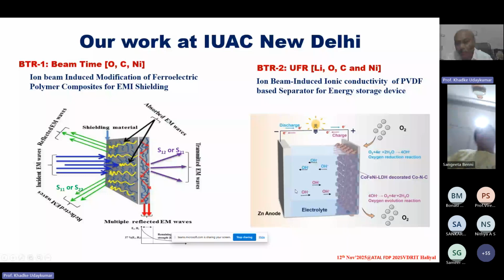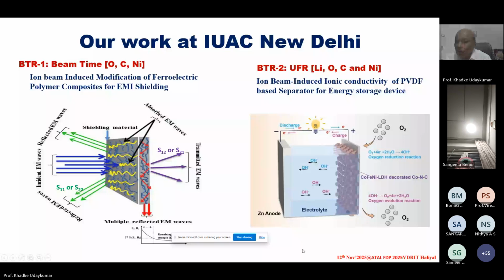So what our team has thought of is to put a layer between these electrodes, but treat those layers with an ion beam so that you can create complete systematic porosity in the material, and through the porosity you can see a movement of the charged particles. So this is the idea. Here I used a PVDF film and completely irradiated it with an ion beam. Irradiation has been done. Whereas in the case of EMI shielding, what we did is implantation. The ion beam should go and sit inside. It should create a porosity and then go and sit on the inner side.